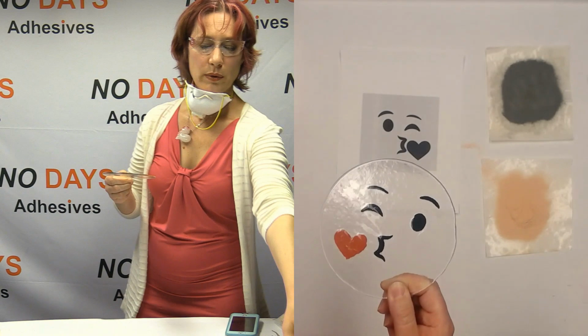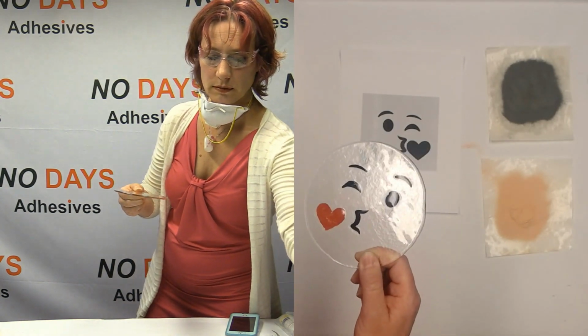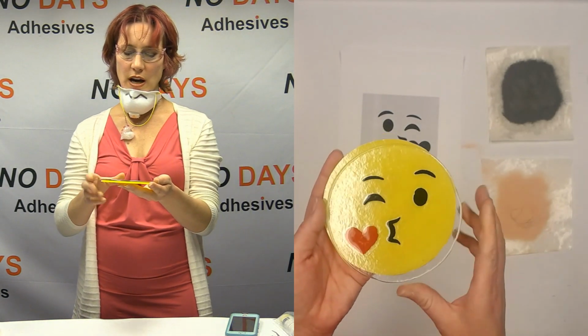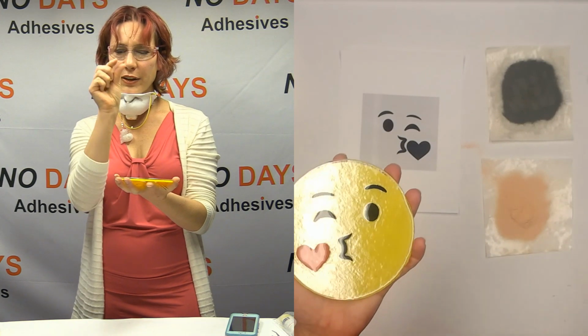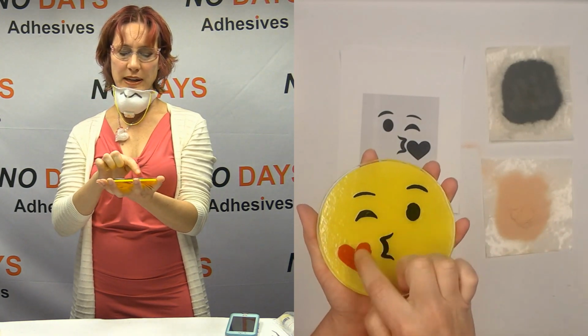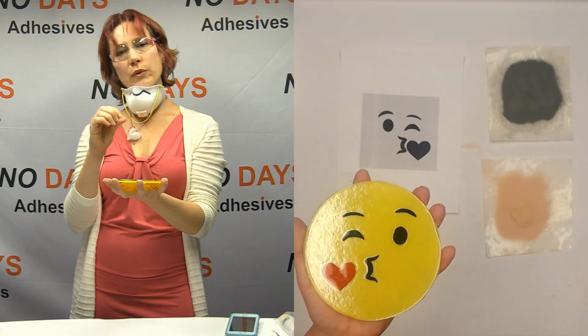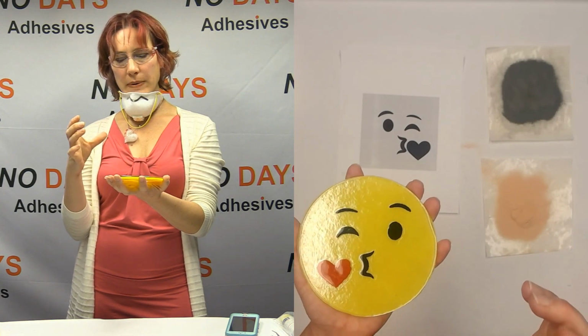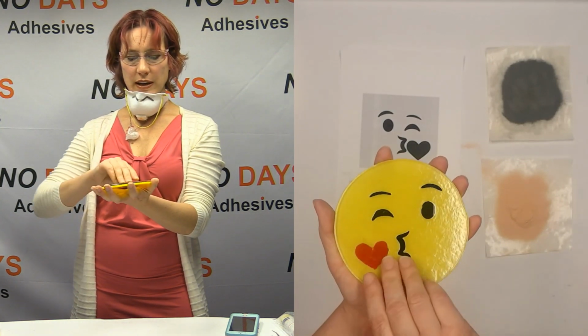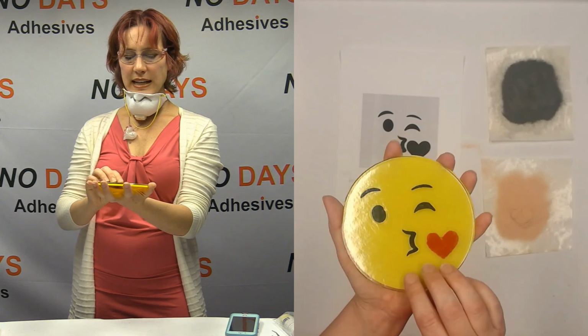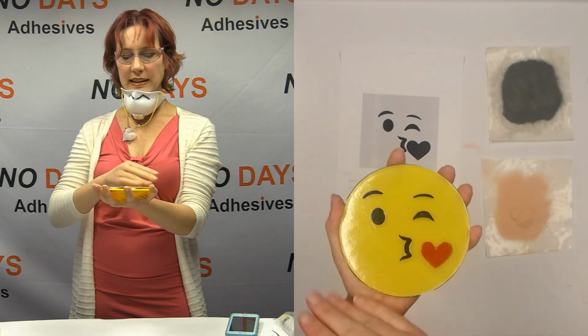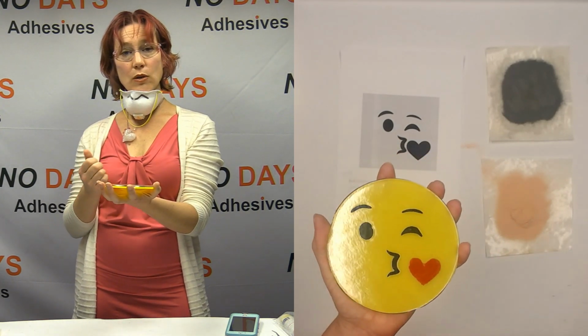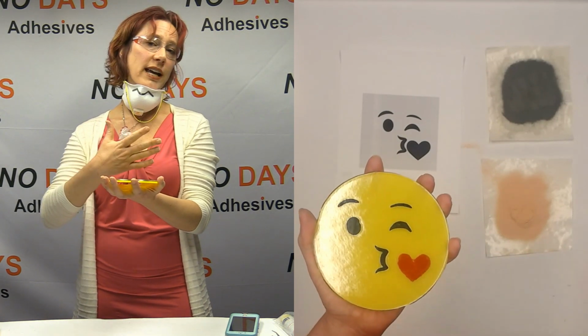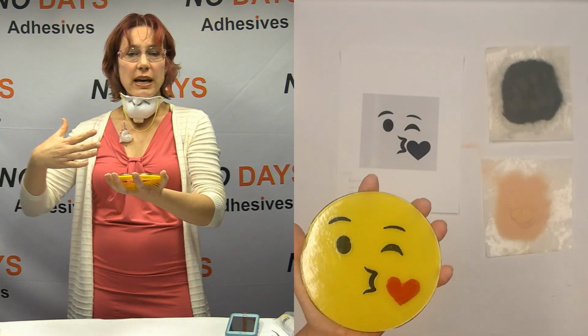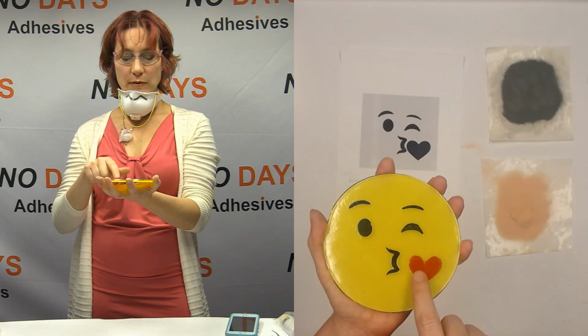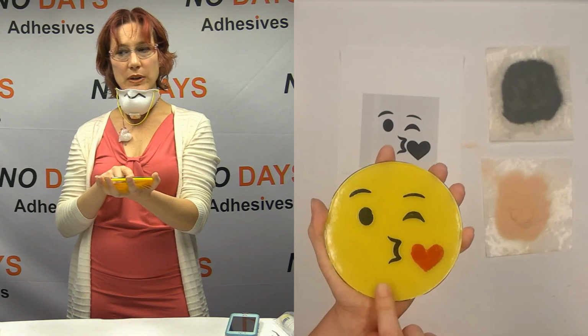Now, typically if I'm working with smaller pieces, thinner designs, I don't have to worry so much about that becoming an issue. But once you start working with a little bit bigger designs with the fiber paper, or with the powder wafers, sometimes that does become an issue, because as the glass is melting, it's trying to get to be 1/4 of an inch thick. So it's trying to move to make that 1/4 of an inch thickness, and if it moves anywhere, that's where you might get some of those tears.